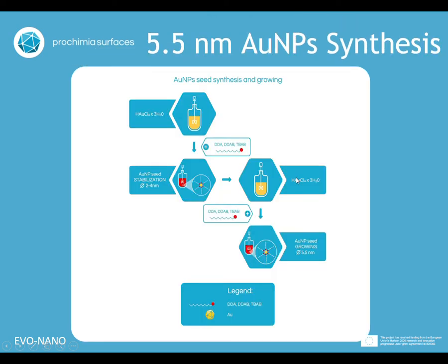In general, the preparation of gold nanoparticles with different sizes can be performed stepwise. Frequently the gold salt is reduced in the presence of a stabilizing agent. We use dodecylamine as the stabilizing agent, and in the presence of didodecyl dimethyl ammonium bromide and tetrabutyl ammonium borohydride as the reducing agent, we obtained gold nanoparticle seed solutions, and these seeds were used for the further reduction